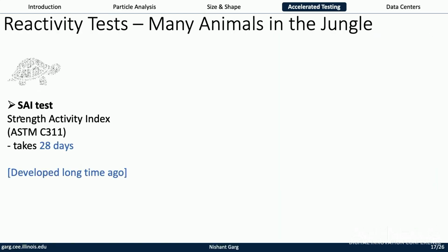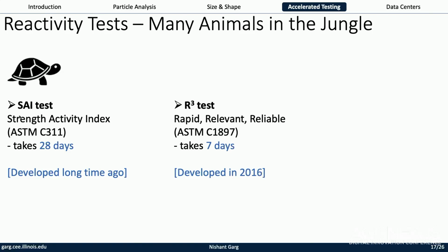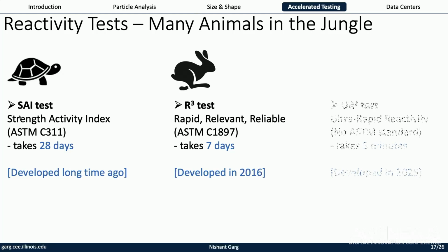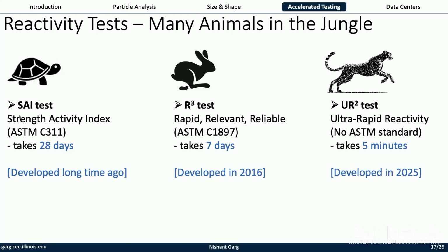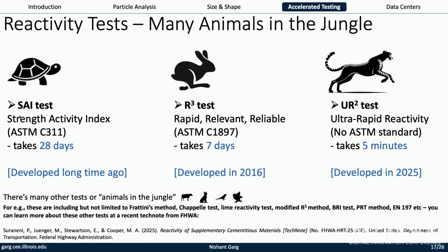So if you look at reactivity tests, without going too much into detail, there's the strength activity index test, which takes about 28 days. I call it the tortoise. There was the R3 test developed 10 years ago. It's a little bit faster, can be done in a week. And then the test that my lab has developed, we call it the UR2 test. I'm still thinking about what animal to call it, but we're going with this fast-running cheetah. And there are many tests, many animals in the jungle, right? If you're interested, you can read this paper.